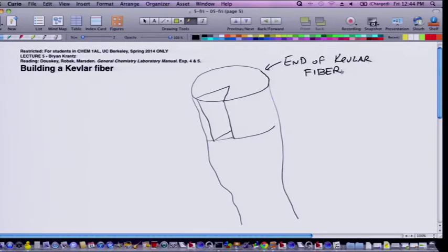And I've cut it away so you can imagine that these benzene rings and their bonds are parallel on this axis. Okay, so these polymer chains are doing hydrogen bonds in these planes. And then as you go around the wedge, it's not clear exactly how it resolves in the middle. But these sheets of aromatic rings in this hydrogen bonding array are going to actually then stack on one another and be glued together by aromatic interactions between the sheets.